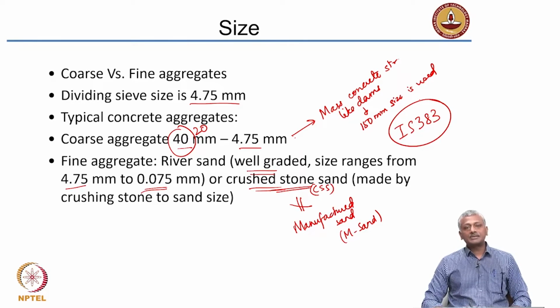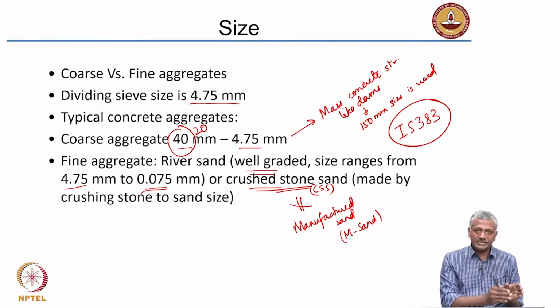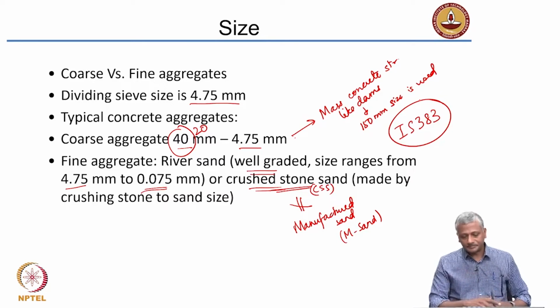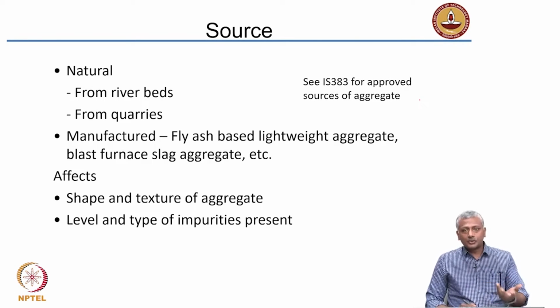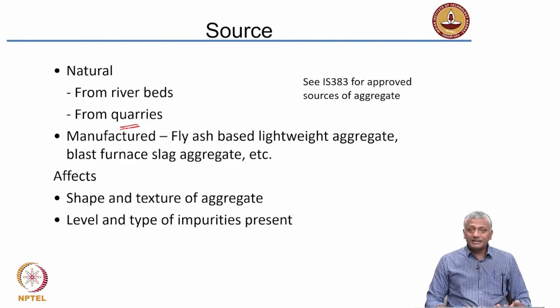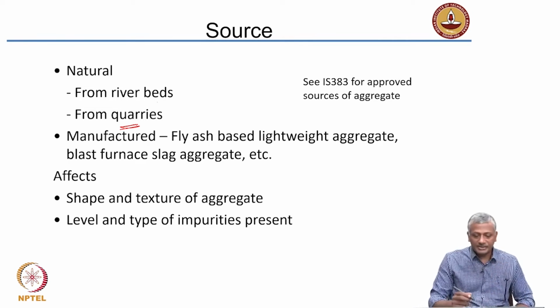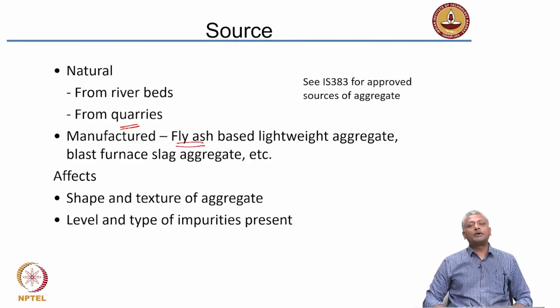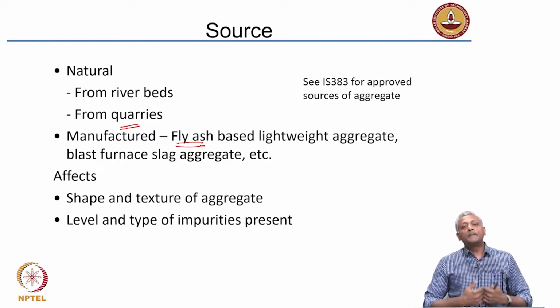IS 383 is the standard for aggregates in concrete. It talks about size, shape, texture, it talks about source and so on. Based on that you can figure out whether the material that you are using is fine aggregate based on river sand or crushed stone sand or manufactured sand. Again as I said, the source can be from natural sources like riverbeds. You can collect the material from riverbeds or you can collect it from quarries. Stones are typically broken out from quarries. Manufactured sand is actually the sand which is obtained from artificial sources. For example, if you take fly ash which is collected from thermal power plants and you fuse the particles together to make an aggregate sized object, that becomes a manufactured fly ash aggregate.